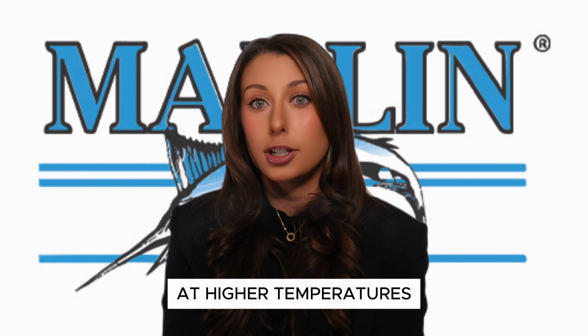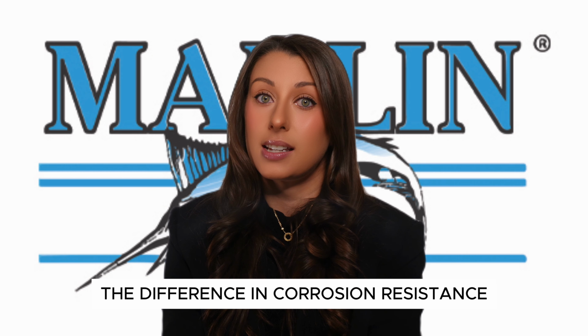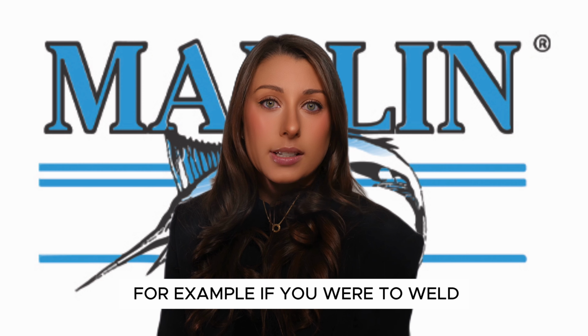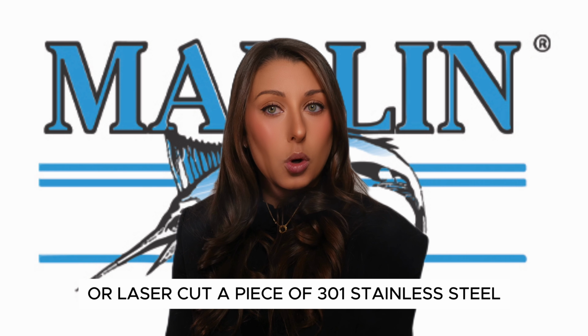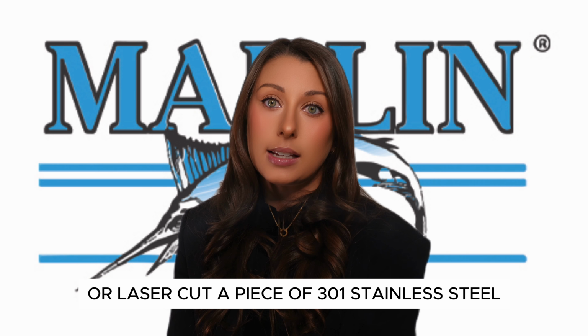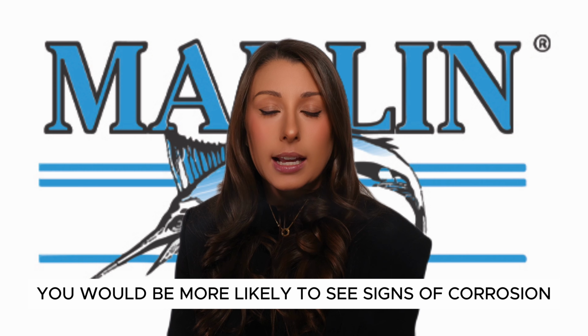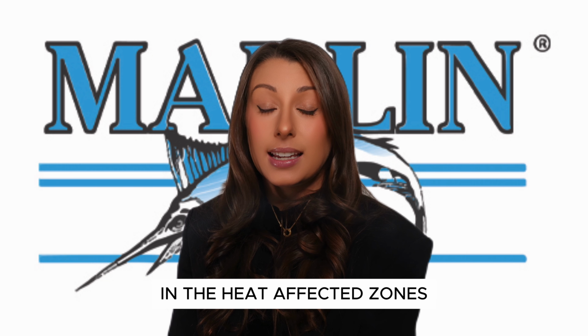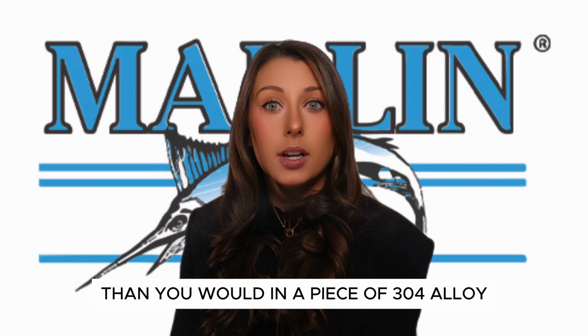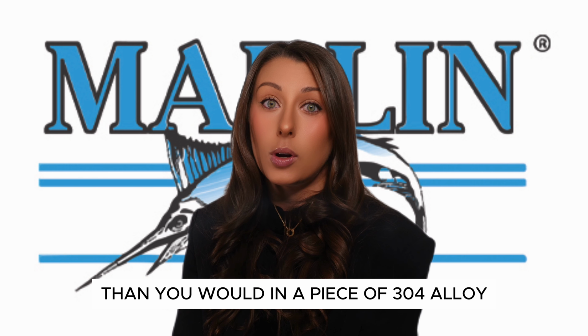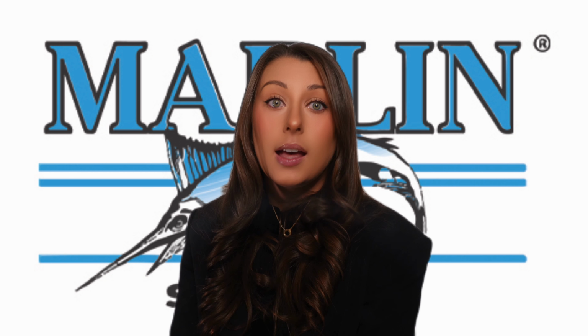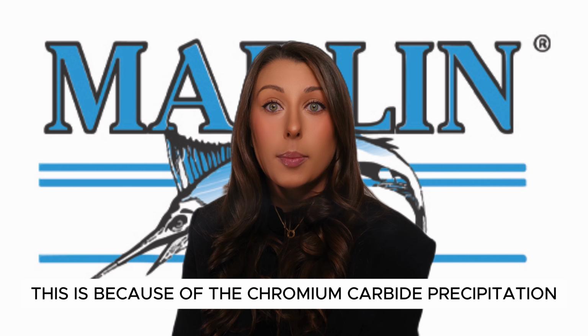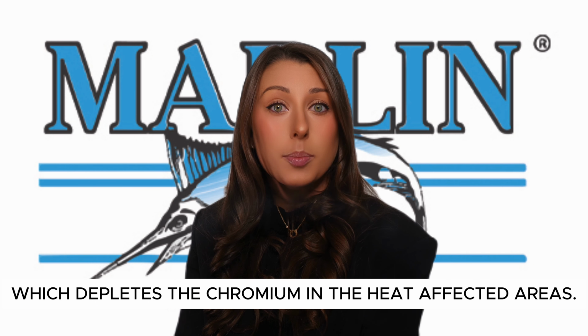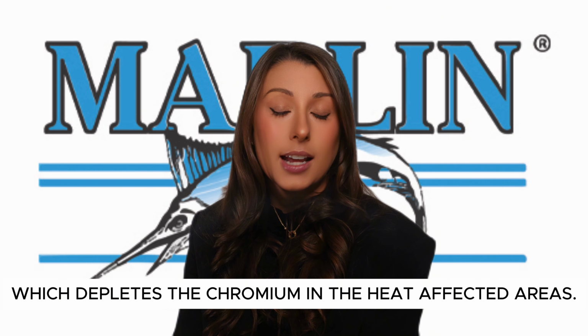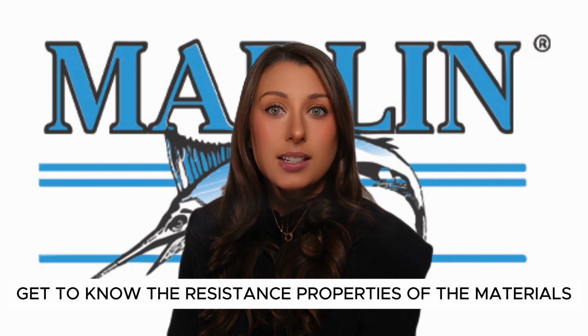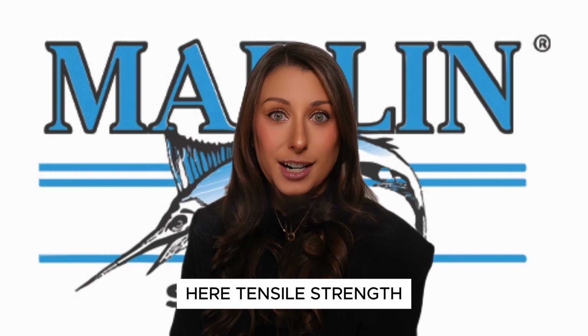At higher temperatures, the difference in corrosion resistance is more pronounced. For example, if you were to weld or laser cut a piece of 301 stainless steel, you would be more likely to see signs of corrosion in the heat-affected zones than you would in a piece of 304 alloy treated in the same way. This is because of the chromium carbide precipitation, which depletes the chromium in the heat-affected areas. Get to know the resistance properties of the materials here.